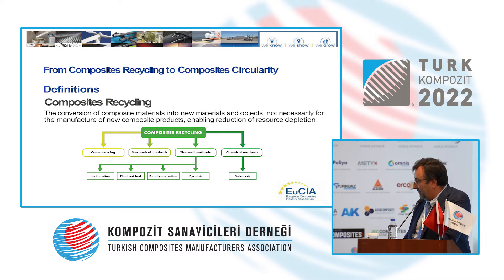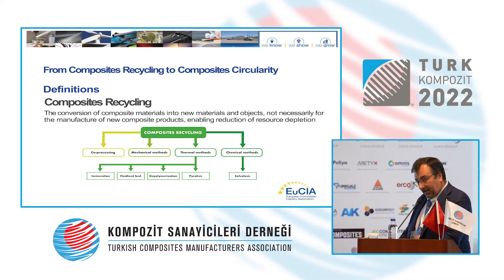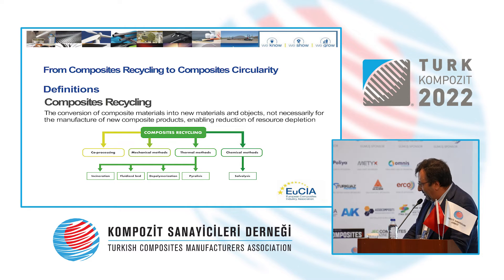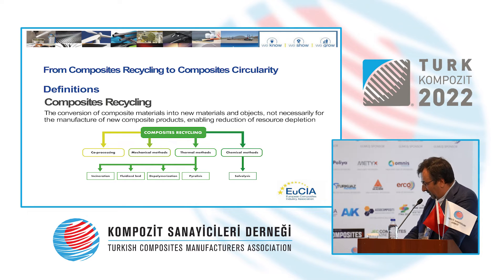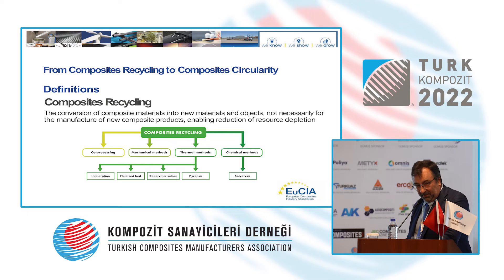There are several different options for composite recycling, ranging from coprocessing into cement kilns and mechanical grinding to thermal decomposition of the resin and chemical decomposition of the resin to recover the fibers — known as solvolysis. The appropriate option depends on the specific needs of the application.